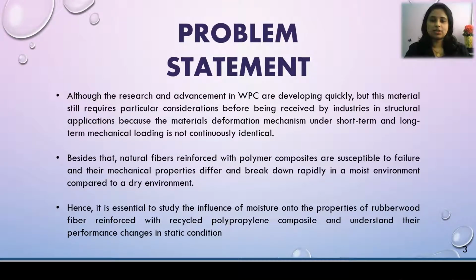Although the research and advancement in WPC are developing quickly, this material still requires particular considerations before being accepted by industries in structural applications, because the material's deformation mechanism under short-term and long-term mechanical loading is not continuously identical. Besides that, natural fibers reinforced with polymer composite are susceptible to failure, and their mechanical properties differ and break down rapidly in a moist environment compared to a dry environment.